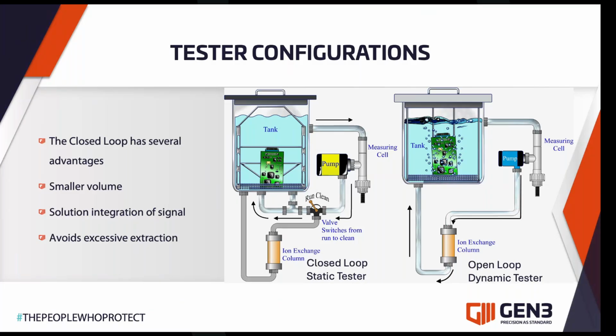The big thing also is that if you have a closed loop system, the contamination slowly builds up, so it's very easy to measure your endpoint with the test. With an open loop system, you're integrating an electronic signal, and as we get close to the end of the test, we're into noise issues. It's very hard then to get to a precise endpoint and know when to stop the test. So the test could go on for a longer time. It could continue to pull out extra ions from the substrate, which you don't really want to see.